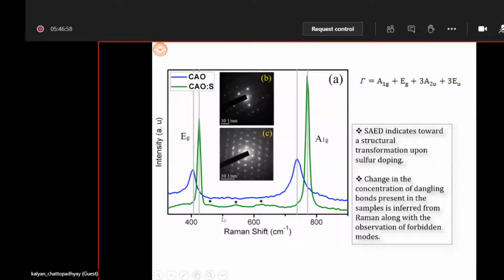Now, as soon as sulfur was introduced at the oxygen site, the anionic site, you see a number of important changes. First of all, both the peaks are shifted to higher wave number, and there is a significant increment of intensity and decrement of FWHM. Interestingly, some star-marked peaks start to appear. These are because of the breaking of the local symmetry, as I already indicated, due to the sulfur incorporation. So the selection rule gets relaxed, and some peaks which are otherwise forbidden start to appear. Also, the background decreases. Whenever there is a decrease in background, you can say that metallicity in the system has increased, meaning the carrier concentration has increased. So all these suggest that the correct valence band dispersion has been achieved, and it should show some reflection in the electrical properties.